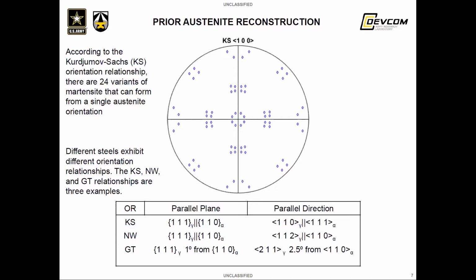This table lists a few possible orientation relationships and depicts them as the set of equivalent crystallographic planes and directions between the parent and daughter structures. For AF9628, the Kurdjumov-Sachs orientation relationship holds best, which is often true for lath martensitic steels.